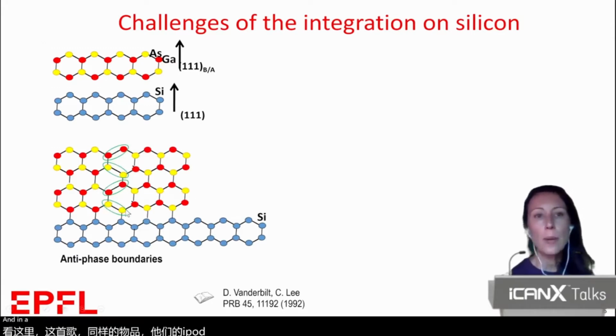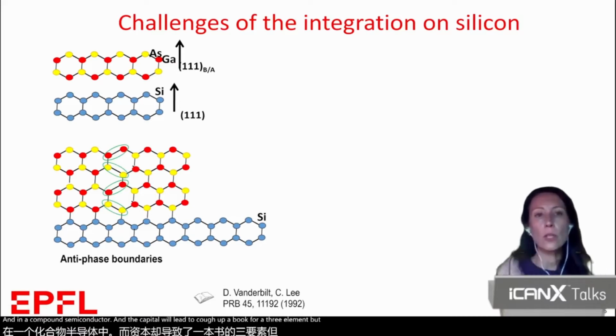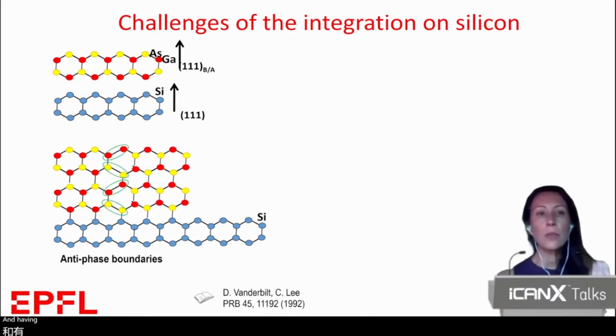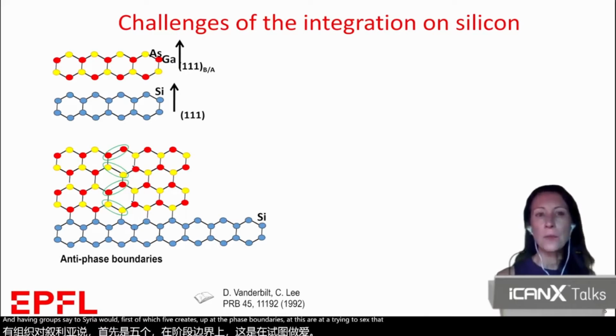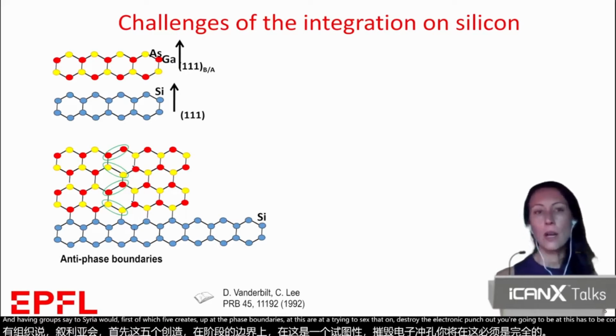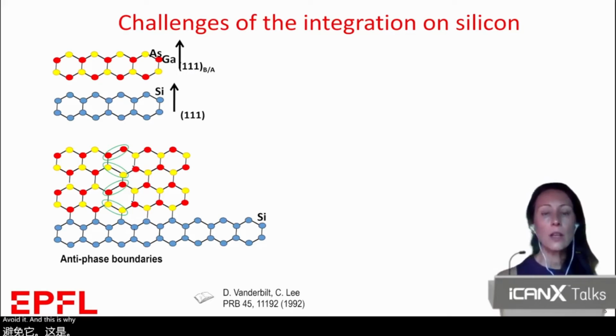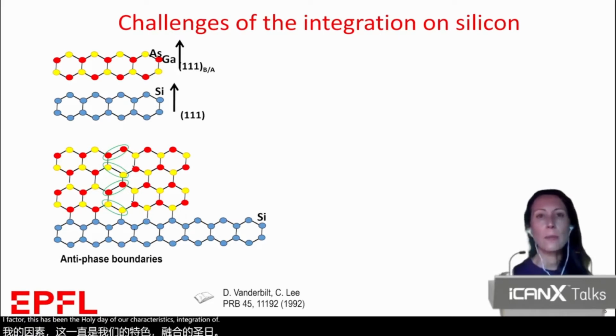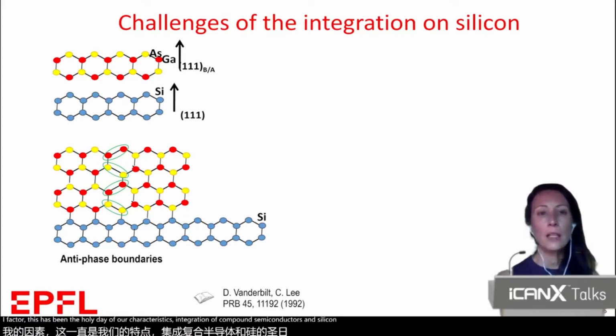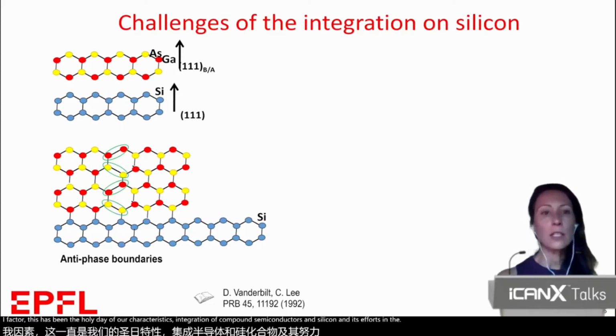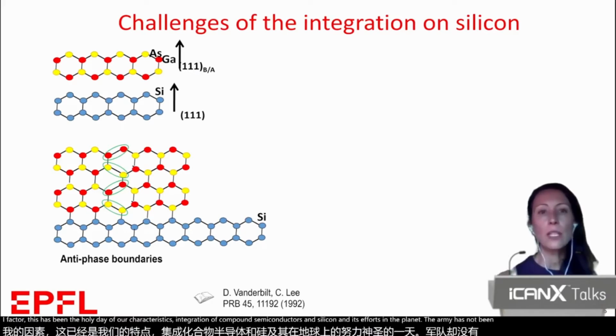In a compound semiconductor, we need to have a group III element always bonded with a group V, and having group III to group III or group V to group V creates antiphase boundaries, and these are electronic defects that destroy the electronic functionality of the material. So this has to be completely avoided, and this is why the integration of compound semiconductors on silicon has been the holy grail of optoelectronics. In the planar realm, it has not been completely solved yet.